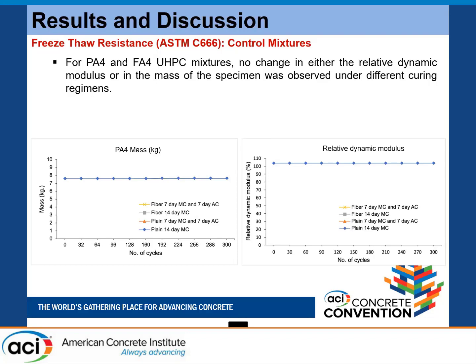And relative dynamic modulus never falls below 100%. For your information, for conventional concrete, if the relative dynamic modulus of any specimen falls below 60%, we classify that specimen as failed under freeze-thaw conditions. But ASTM C1856, related to UHPC material, says the relative dynamic modulus should not fall below 90%, because it's a high integrity material. So it's not 60%, the threshold number is 90%. But in this case, we have seen there is no drop in relative dynamic modulus.